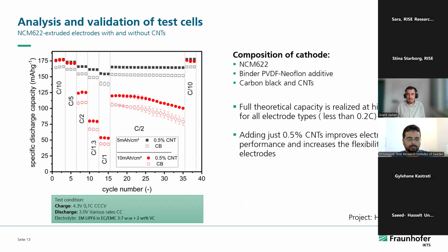Here, just an example of the analysis and validation in a cell. Here we used NCM 622 as the active material, and we did with and without carbon nanotubes. In this case, we were presenting 5 milliampere hour per square centimeter and 10 milliampere hour. So here we can see that the extruded electrodes, also at 10 milliampere hour per square centimeter, still have a good specific discharge capacity.